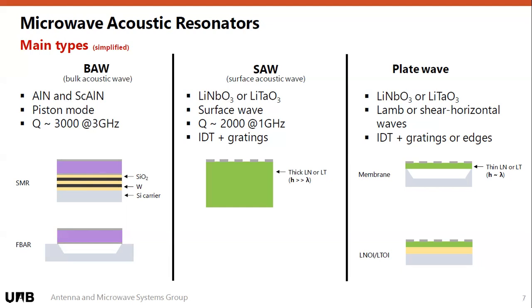So surface acoustic waves, in this case, they use Rayleigh waves on thick layers. In this case, it's normally a wafer, mainly of lithium niobate and lithium tantalate. These are the traditional materials. This was developed initially at really low frequencies for IF filters, and then it got scaled up to the 2 gigahertz range. It's considered that the barrier between BAW and SAW is actually at the 2.2, 2.3 gigahertz range. So they are complementary technologies.